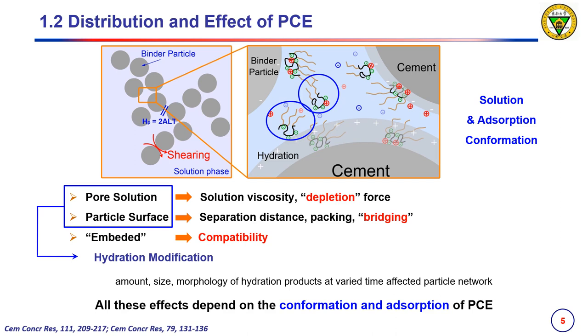The last part of PCE molecules is embedded by the hydration products, which is a situation related to compatibility. Interestingly, both the solution and adsorption parts will affect the hydration process and finally change the rheology properties. It is important that all these effects really depend on the conformation and adsorption behavior of PCE.